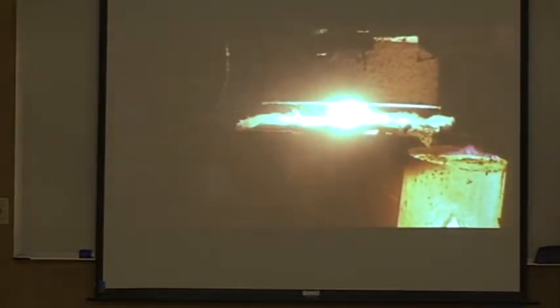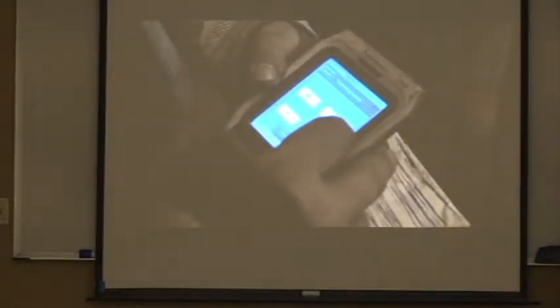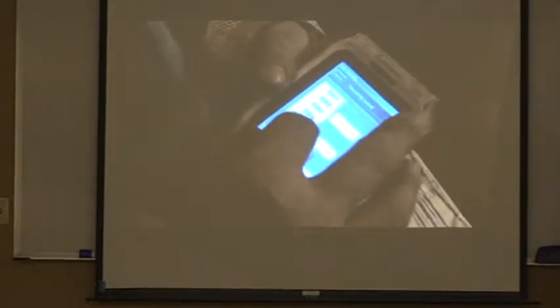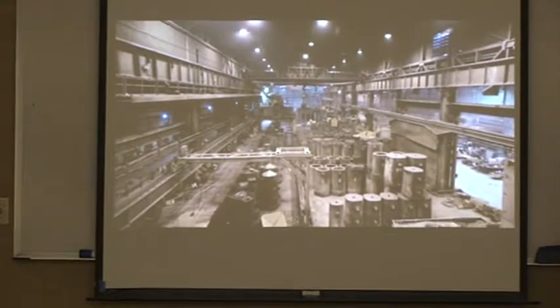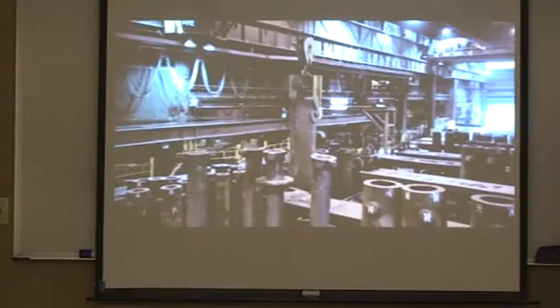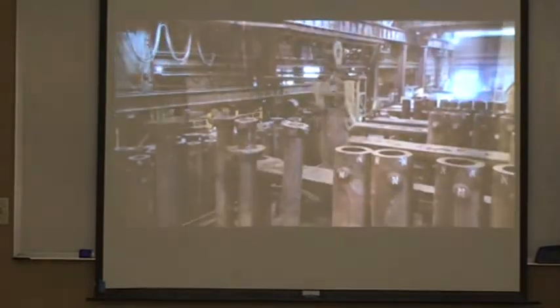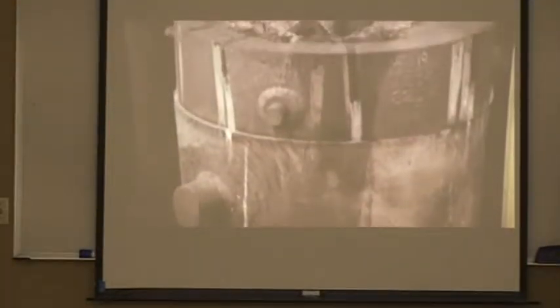As part of our continuing effort to produce high-quality clean steel, argon shrouding is used to help protect the liquid steel stream from reoxidation and hydrogen pickup during the teeming process. All ingots produced are bottom poured at a controlled rate, and steel pourers utilize handheld data entry devices to continually monitor the teeming operation so that maximum consistency can be achieved. EQS maintains a large variety of mold shapes and sizes in order to accommodate the various ingot requirements of our customers.